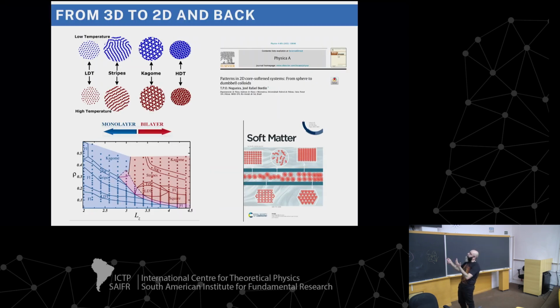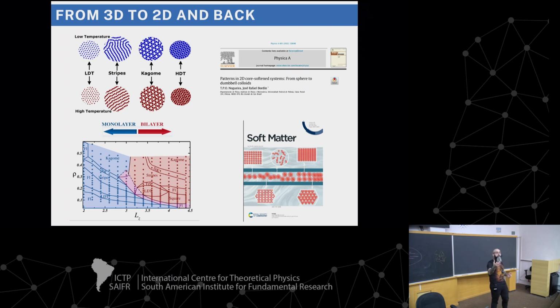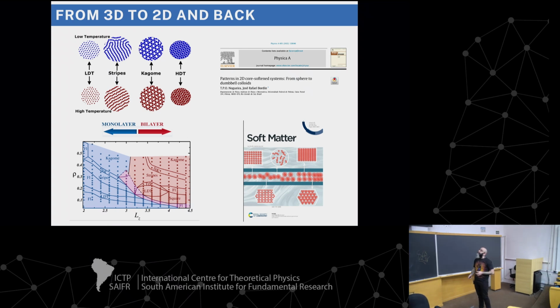Okay, we also did some work with 2D and almost 2D systems, and this is interesting because it's connected with what Carol was saying at the end of his talk about the patterns that we can get in these Hairy-Ball systems. If you have only one layer, for this specific potential, we can have a low-density triangular phase, this kind of stripe or labyrinth phase, a Kagome crystal, or a high-density triangular phase.